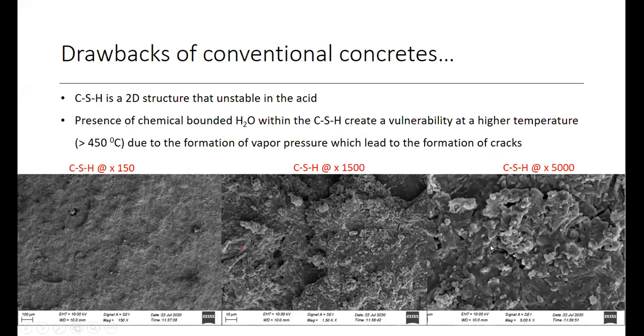So you can see here there are a lot of cavities or porosities. Suppose water can accumulate inside the porous media at high temperature, like 450 degrees. Then very high pressure moisture or very high pressure vapor could be generated inside those pore structures. That could lead to a failure of the concrete. That is the reason conventional concretes are not very stable at higher temperatures. The reason is that they are formed with C-S-H gel.